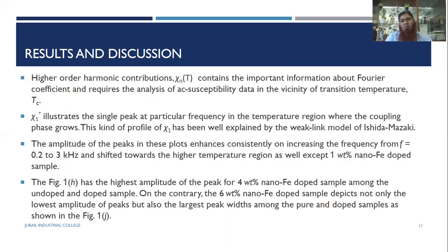The imaginary part gives a single peak at a particular frequency in the temperature region where the coupling phase grows. We got the peaks at certain temperatures, and this kind of profile has been explained by the weak link model of Ishida and Mazaki.